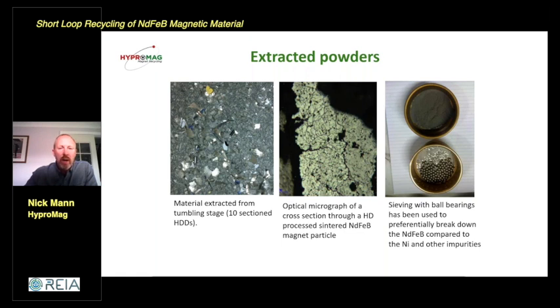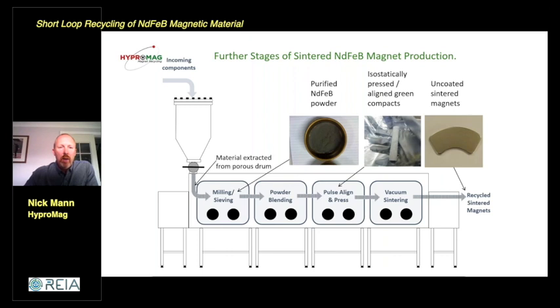So then we can do a mechanical sieving using some steel balls just to help break that NdFeB up further. The NdFeB breaks apart more preferentially to anything else that's there, and we can basically sieve out the nickel coating, we can sieve out the plastics and the screws, and we end up with a relatively pure NdFeB powder, which can then go back into the magnet manufacturing process. So again, we can mill or sieve that powder further as we need to, blend as we need to. We can then pulse align and press, and then the sinter, the shaping and the magnetizing of the end product to make a new magnet out of that recycled powder.